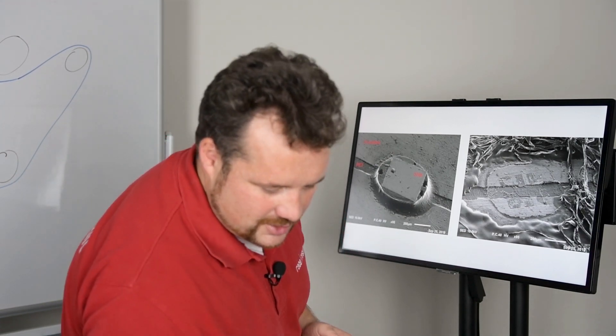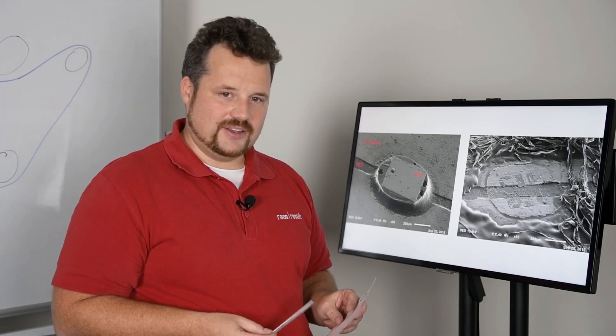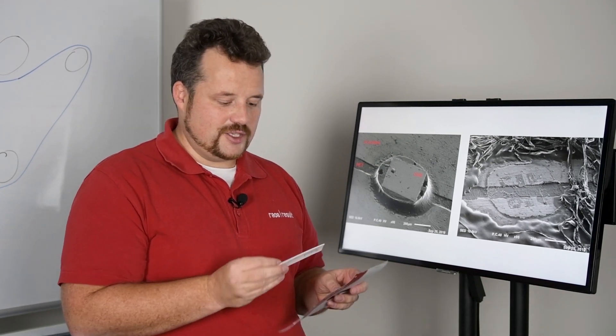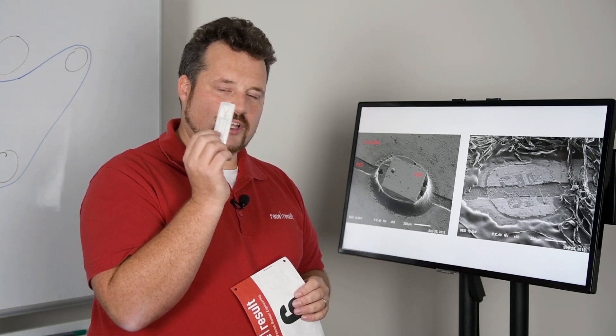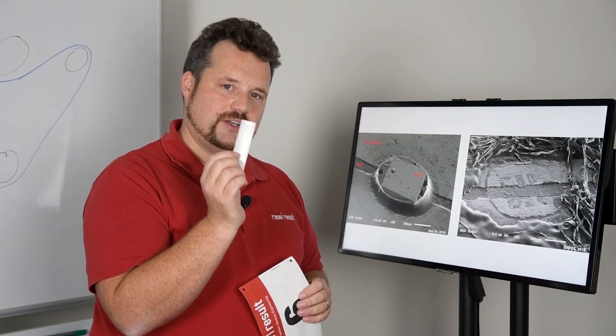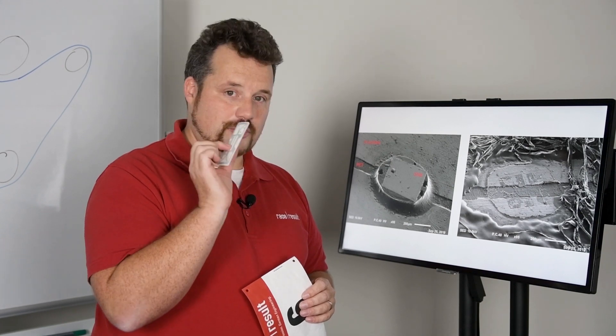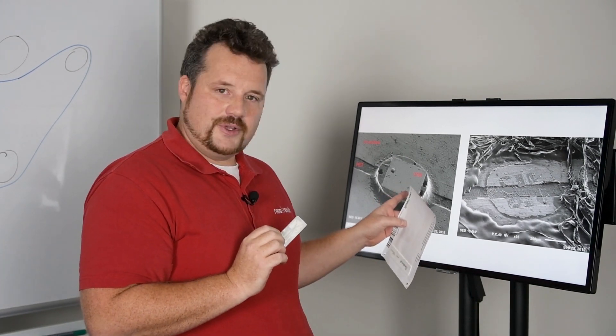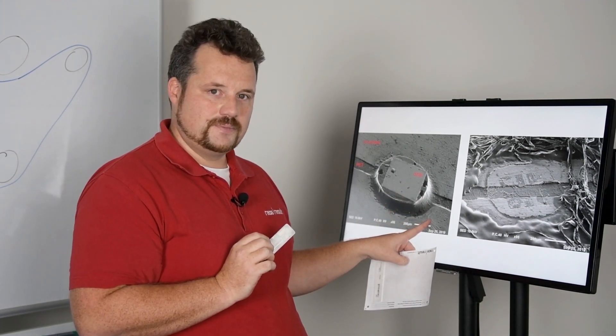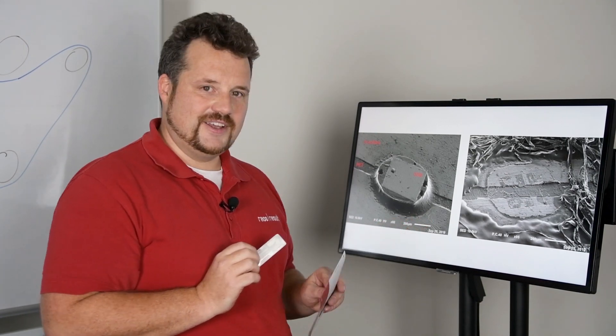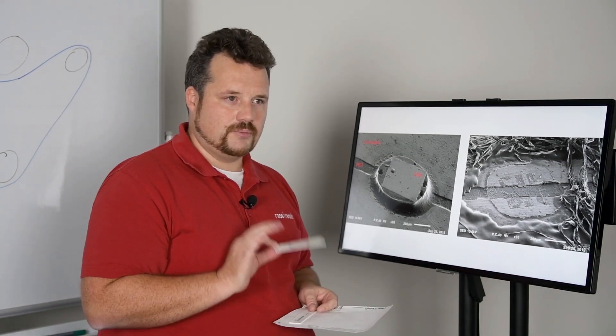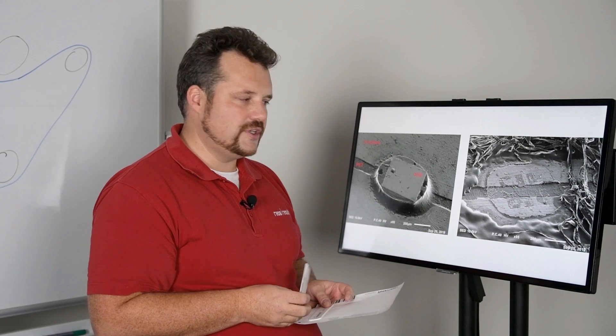What we then got is a sample of one bib where this happened, where we could see residue from the adhesive on our transponder on the other side of the bib with some dirt on it. It was pretty clear that this chip was placed on the other side by the helper doing the chip attachment. When we then interviewed our customers of what they had done with the chips that failed, it was pretty obvious that this was actually the problem. What we found, which might sound like a very simple thing to find after all of this, was that all of the transponders that failed were taken off the bib again. The issue here is that with our glue that we have on the back of our transponder, we found out that after a certain time of curing, the glue on the back of our transponder is stronger than the glue between the chip and the aluminum foil.